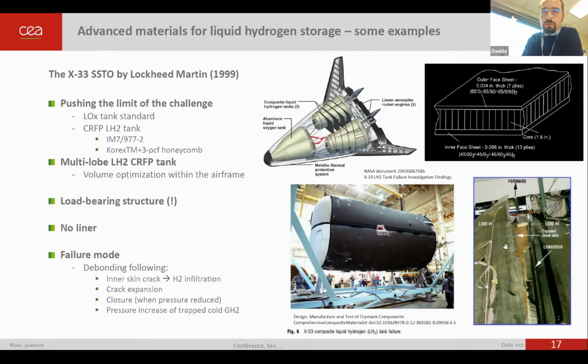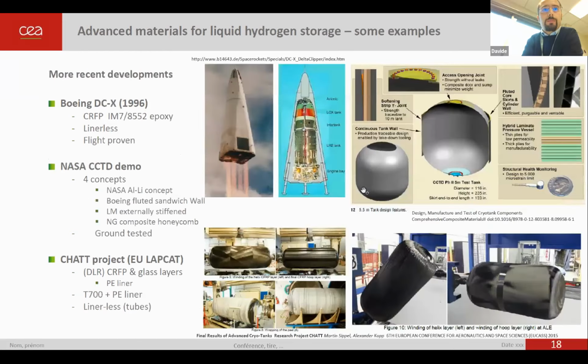So the fact that there was no liner led to micro cracks, which led to the accumulation of liquid hydrogen within the structure of the CFRP panel. And then due to the heating, the pressure within the panel increased, and basically the structure of the tank exploded. So that's the first. Yeah, sorry. Can you conclude in 2 minutes? Yeah, of course. I'm almost there.